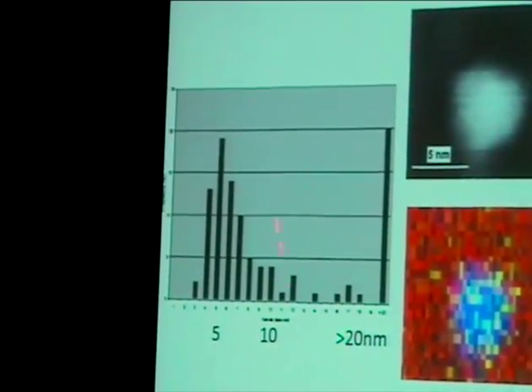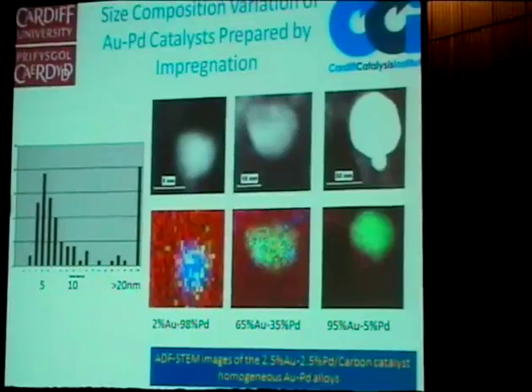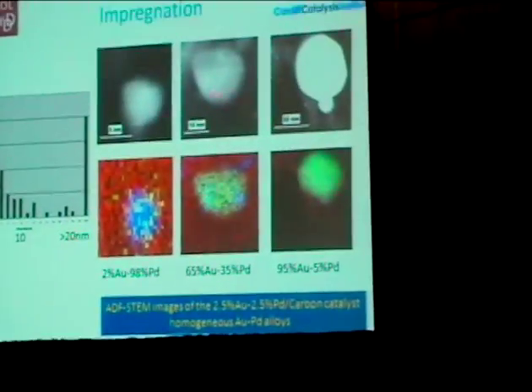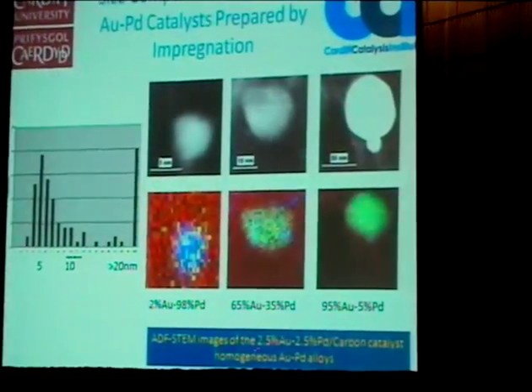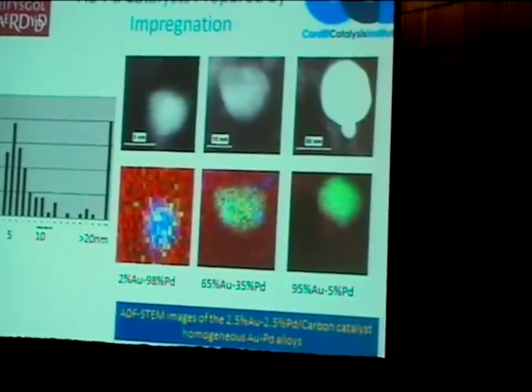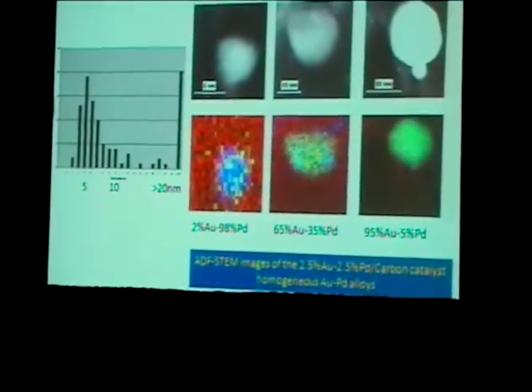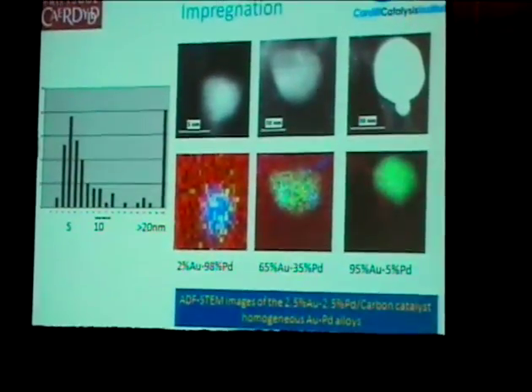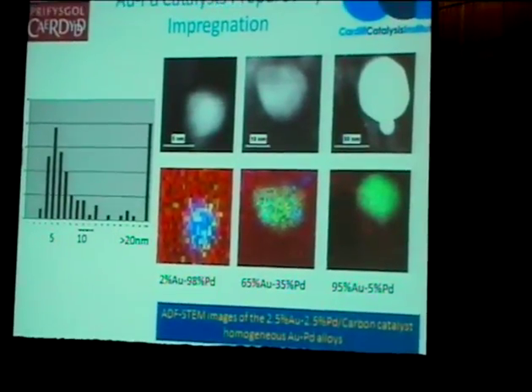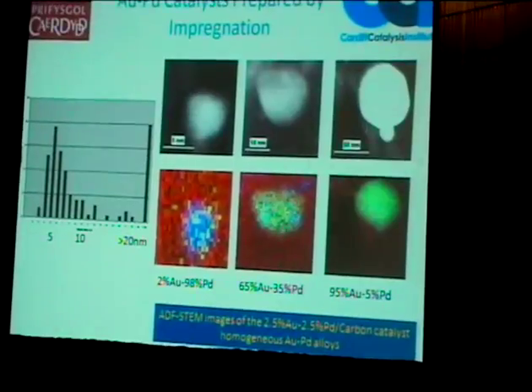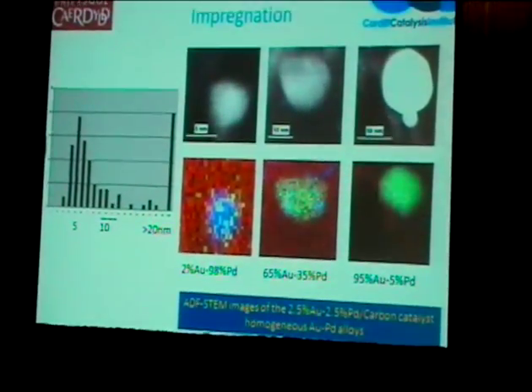So one of the problems with using these gold-palladium catalysts for this reaction is that, as well as having a very wide particle size distribution, as you can see here, from 2 to 3 nanometers all the way up to 20-plus nanometers, as I showed earlier, we get a composition variation with size. These small particles tend to be very palladium-rich. As we increase the particle size to 10 nanometers and 50 nanometers, the particles seem to contain more gold and less palladium. So we have two competing effects: particle size distribution and composition distribution. This is thought to occur through an Ostwald ripening mechanism where the gold is more mobile than the palladium. So the gold will leave the smaller particles and enter the bigger particles.